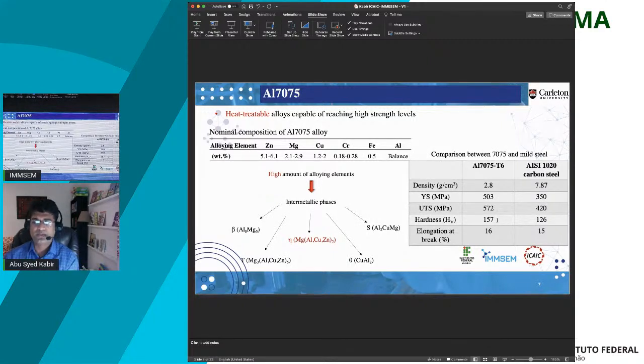Now, the reason why we are so interested about 7075, this is a very simple comparison between 7075 at the peak hardness or T6 heat treatment and the AISI 1020 carbon steel. This is the mildest steel possible. We see that at the peak hardness or peak strength position, we can get higher yield strength, higher UTS, higher hardness, and even better elongation than 1020 carbon steel. Whereas if you look at the density, it's about 1/3 of steel. So that makes a big difference in transportation industry, especially aerospace and automobile industry.